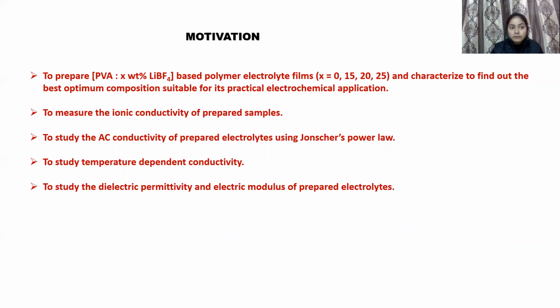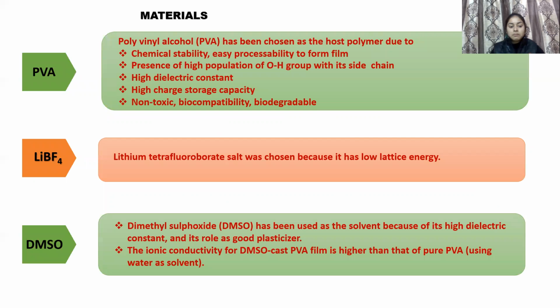The motivation of my work is to prepare PVA and X weight % of LiBF4 based polymer electrolyte films, where X is equal to 0, 15, 20, 25 weight % of LiBF4, and characterize them to find out the best optimum composition suitable for practical electrochemical application, to measure the ionic conductivity of these prepared samples, and then to study the AC conductivity and temperature dependent conductivity, and to study the dielectric permittivity and electric modulus of these samples.